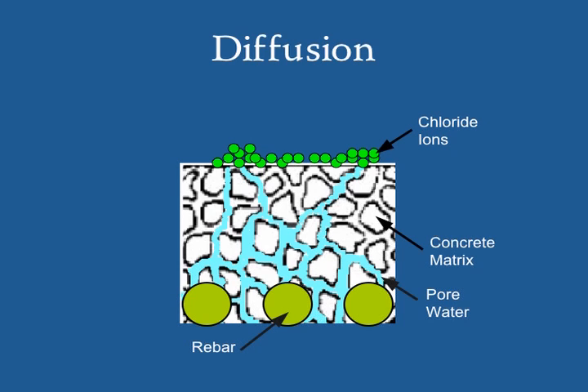Concrete has an internal void structure, which in most cases is at least 90% saturated. The concrete pore water provides a pathway for the chloride ions to enter the deck. As the ions approach the rebar, they can then cause corrosion of the reinforcing steel. Now, when the sodium chloride dissociates or dissolves in water, it produces a sodium ion and a chloride ion. The chloride ion is the one of greatest interest.